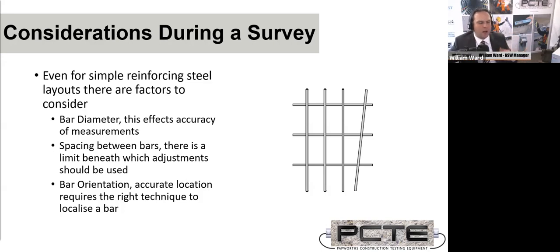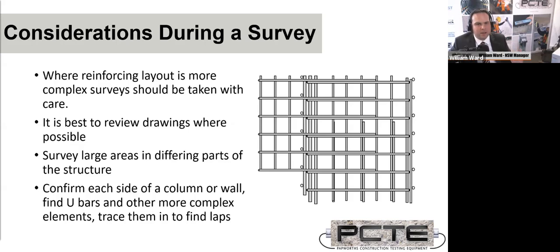Just like with a GPR survey where a single measurement isn't going to tell you the whole story, you want to mark the position of the reinforcing bars several times just to make sure they're all tracking in the same direction if you're using that to set up your measurements. Secondly, where it's complex, it is very helpful to review the drawings or maybe even bring out a radar system so you know the clear regions and you know the less clear regions. And for example, in this situation, there's several places where it's quite appropriate to use a cover meter to establish the depth of the reinforcing steel. These regions being reasonably consistent spacing, this region being far enough distant, even though there's lapped reinforcing bars, similar here. And even here where there's bars close together with a consistent spacing.